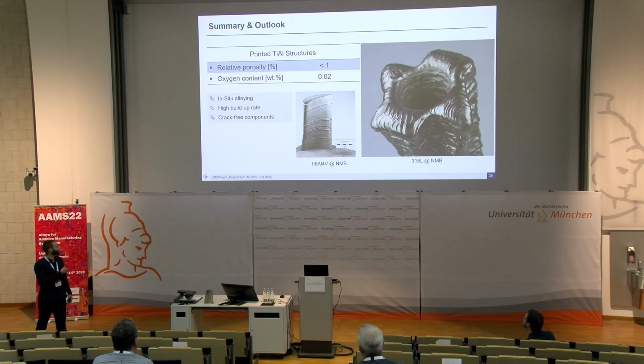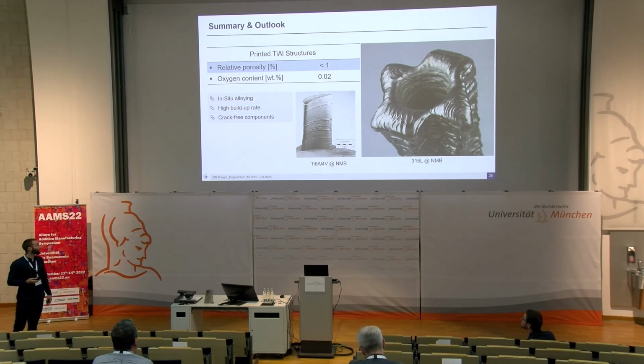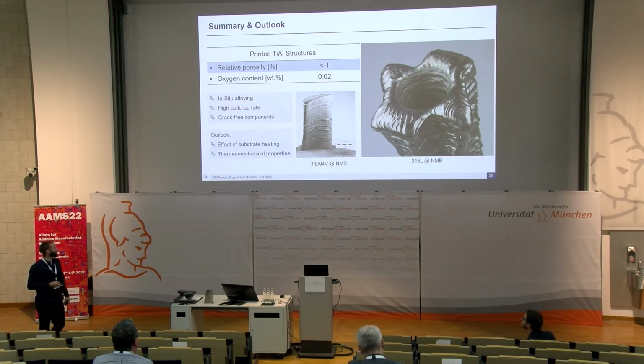What we realized was the in situ alloying of this titanium aluminide. We accomplished it with a high build-up rate, and we manufactured crack-free components. The outlook is that we need to further investigate the effects of the substrate heating, and we need to get to know the thermomechanical properties of these parts.